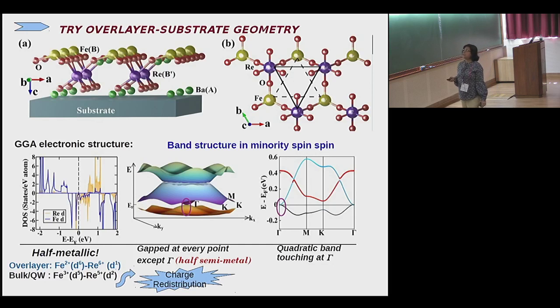rhenium. It still has 3 bands crossing the Fermi level, but as you can see, because of this large trigonal distortion at the rhenium site, which comes from the reduced connectivity of the iron, it splits into doubly degenerate Eg pi and singly degenerate A1g. That is the first important effect that happens in going to such a substrate-like geometry.